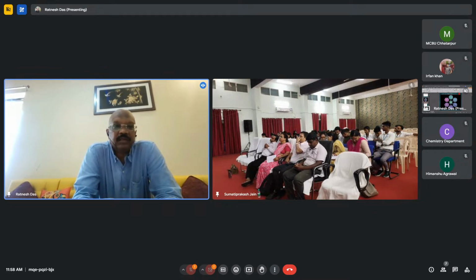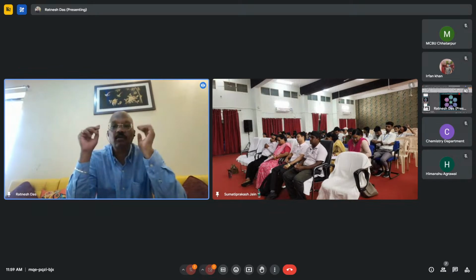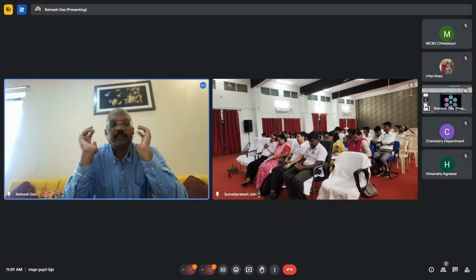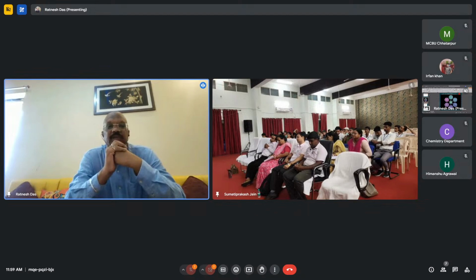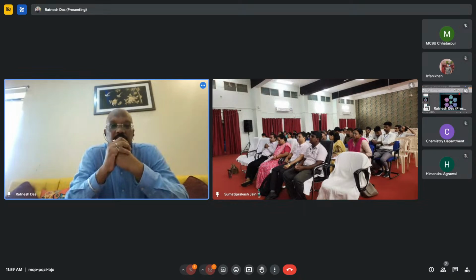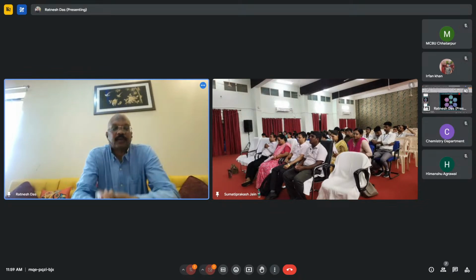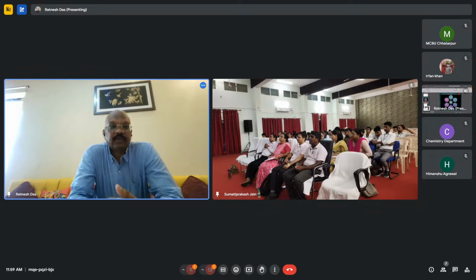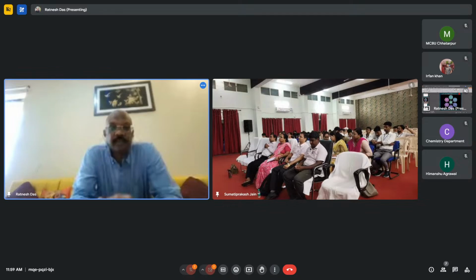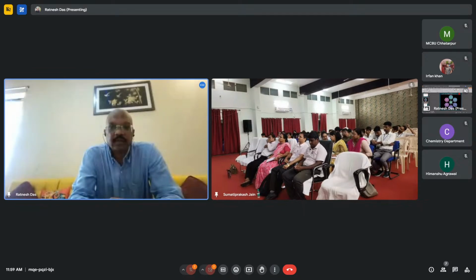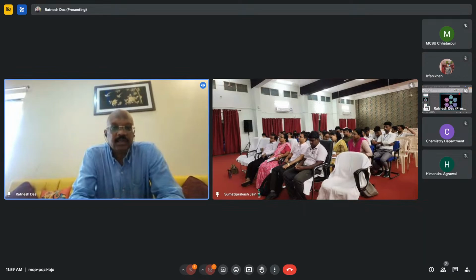And we have done this experiment on an electrochemical workstation controlled by Nova software, a Metrohm Autolab. This is the electrochemical workstation available in our lab. And as you all are aware, the electrochemical workstation is a 3 electrode working system. And pH we have measured. We have sonicated the multi-wall carbon nanotube and copper nanohybrid to effect complete dissolution of the solution.